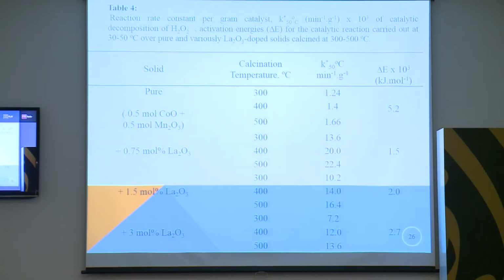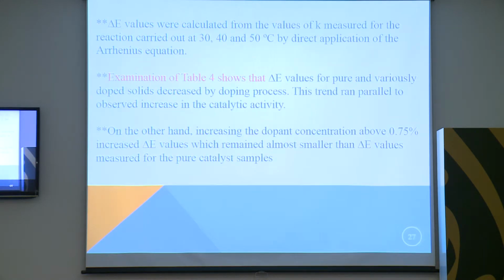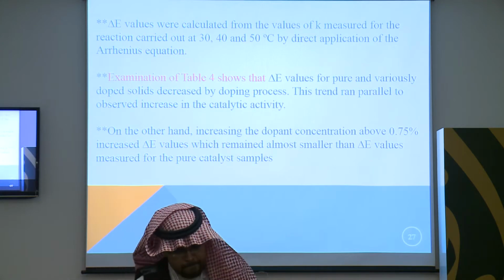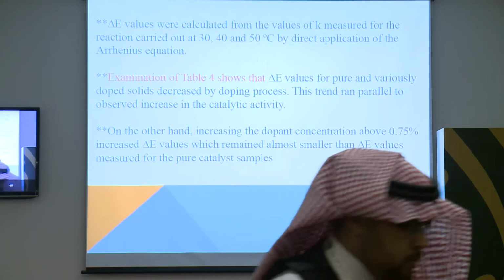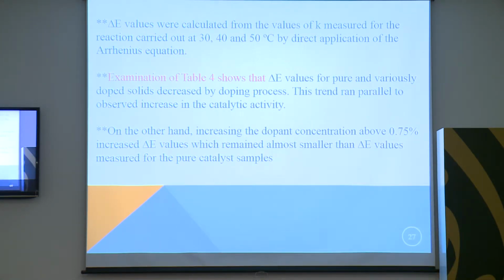In studying the activation energy for the catalytic reaction carried out at different temperatures, the delta E values for the calcined samples show that for all the pure and variously doped solids, delta E values decreased by the doping process. This trend ran parallel to the observed increase in the catalytic activity. On the other hand, increasing the doping concentration above 0.75% increased the delta E value, which remained smaller than the delta E values measured for the pure catalyst samples.